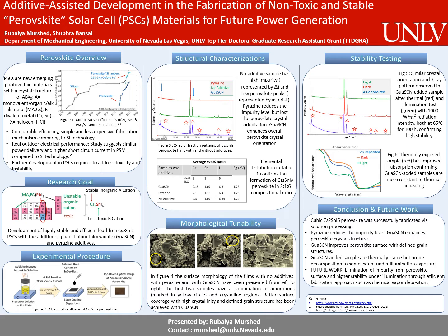My experimental mechanism to fabricate this material in figure 2 is a simple solution processing by heating a mixture of proportionate chemicals and annealing the films in a vacuum chamber with pre-established heating time and temperature. Figure 3 represents the structural characterization of the X-ray diffraction pattern of the perovskite crystal structure.